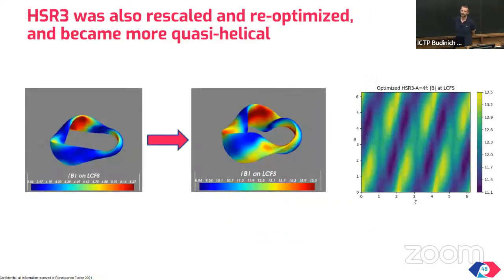These are numerical results, yes. I was a bit fast, but these are numerical results. And the color contours are contours of magnetic field strength on the last closed flux surface. So we took the HSR3, which stands for helical axis stellarator reactor. 3 stands for the number of periods. And this is one of these gigantic designs that I showed in one of the original slides. Gigantic if you do it at low field. If you do it at high field, so you see the field much higher here than here, that allows you to shrink it significantly.